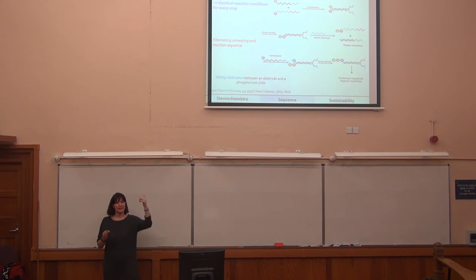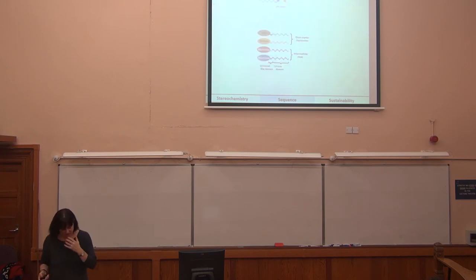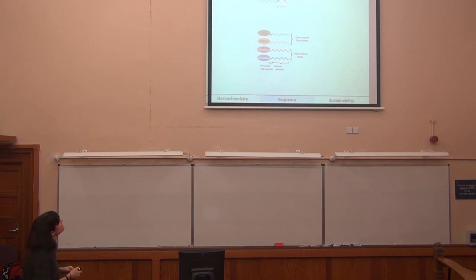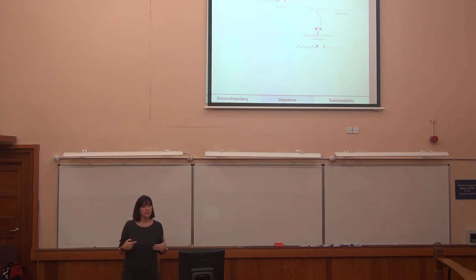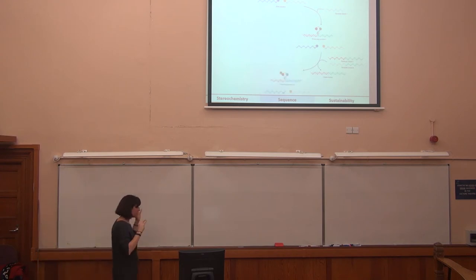One of the difficulties is that we're still doing this in a chemistry way, in that we're adding the reactive groups at each step. It'd be much more elegant to have all the reactive groups in one pot and then add instructions. And that was the next mechanism that Andrew's group developed for us, which we termed junctions. We're now changing around the complementary and distinct regions, so we have much larger unique domains and much smaller universal domains. If you imagine we start with all these adapters in solution, you can add an instruction that says please bring red and green together, that brings two of our four adapters into close proximity, and we form this junction which allows us to do our transfer reaction. Then we can wipe that instruction with a fully complementary strand to our instruction strand, and then add in a new instruction. You can imagine how, with a pot of lots of different adapters, you add in instructions to selectively bring together in sequence the things you want.